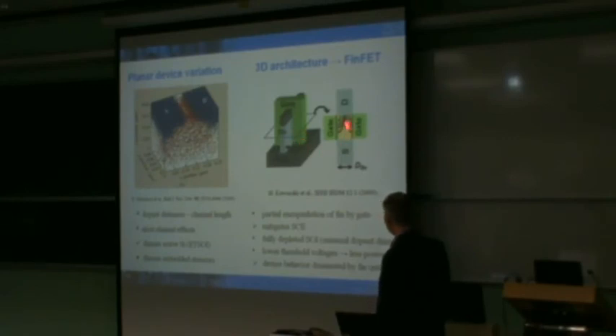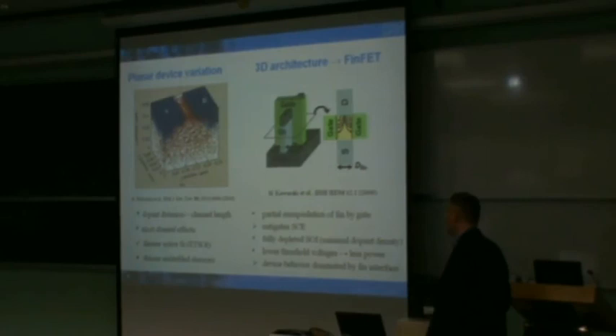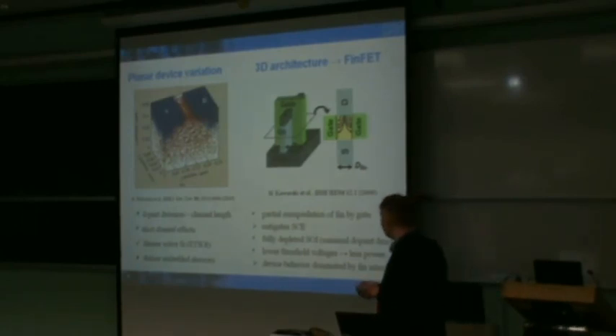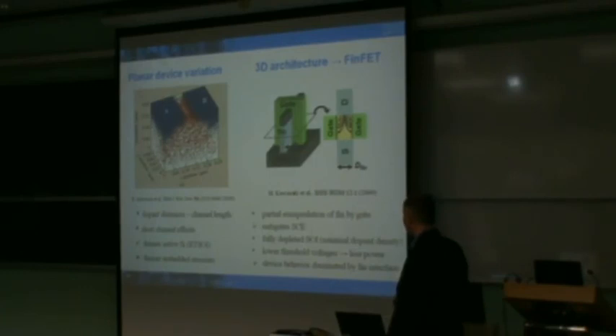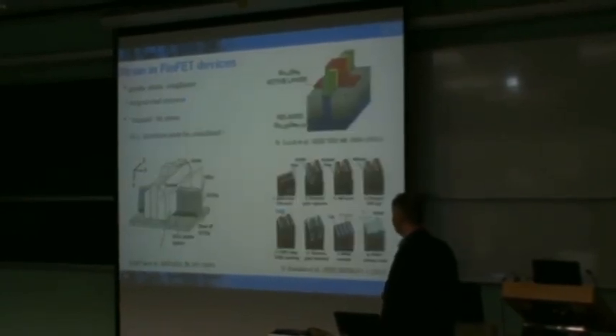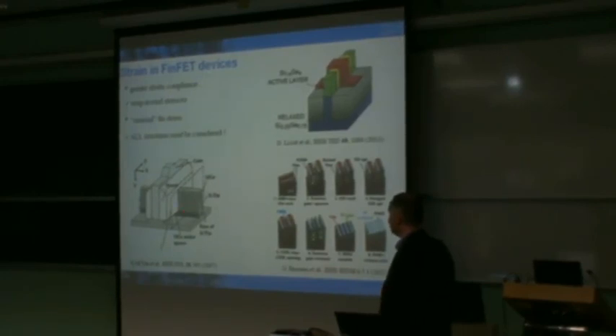And by looking to these approaches that incorporate gate encapsulation, either in this case where we're wrapping around a fin-type structure corresponding to the body, we help to mitigate the short channel effects. But we can actually reduce some of these dopant effects by looking at fully depleted devices, meaning that there are no dopants at all that we intentionally push there. But the key point is that we're able to incorporate lower operating voltages. And so it's called Boltzmann tyranny. The fact that as we're marching on Moore's law here, we're getting to the point where we're not able to really control the devices at the power levels that we require to maintain a usable device. So there are various techniques that incorporate stressors within these types of fin-type structures.